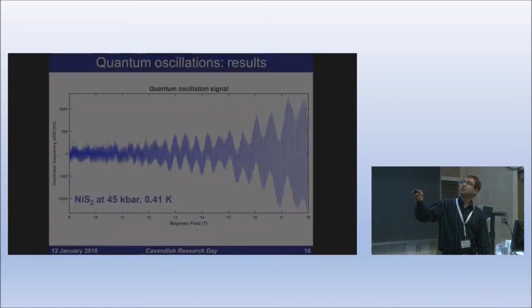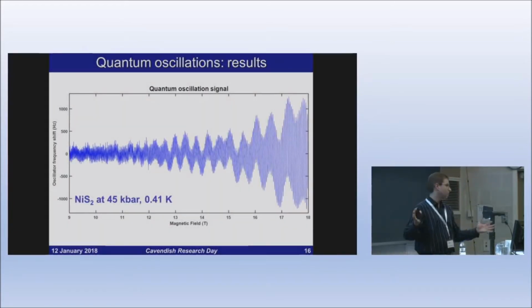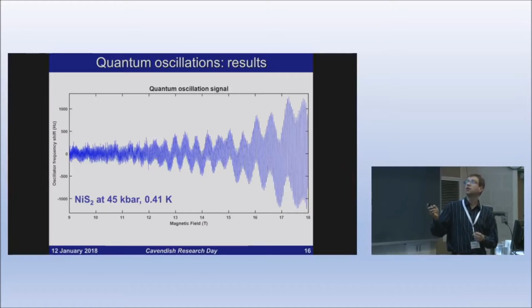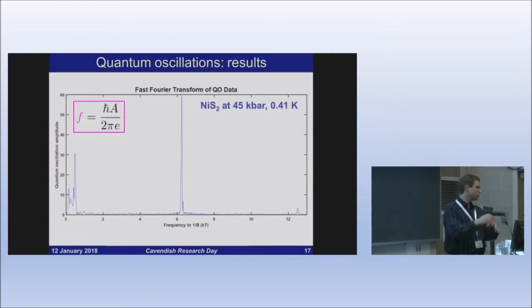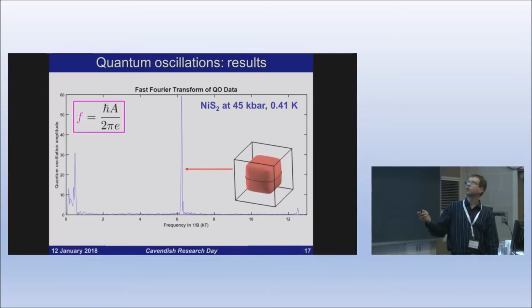And what do we get in the end? Well, we get a quantum oscillation signal like this at every pressure we take and every temperature. But what we want to do is, of course, extract the frequencies and the amplitudes at each frequency. The frequencies are going to be proportional to the areas of these orbits. We see some down here at low frequency. Most prominently, we see this peak around 6 kilotesla, which density functional theory suggests would come from a cube-shaped Fermi surface pocket, a hole-like pocket, or a sheet, rather. And we're going to focus on this for the rest of the talk.